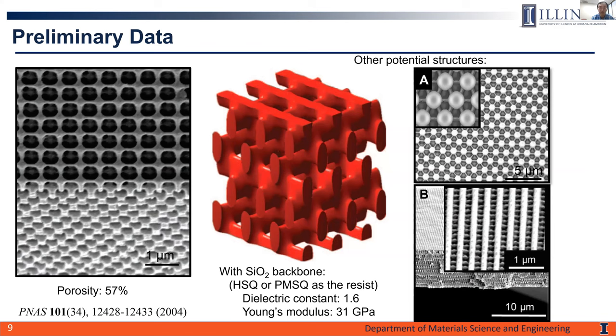So for example, in this case, we can generate a structure with porosity up to 57%. And based on the simulation, it will give an effective dielectric constant down to 1.6. So it's below the target of 2. And at the same time, we're also going to maintain a pretty high Young's modulus of 31 gigapascal. So that's only 3 times lower compared to bulk silicon dioxide. So these properties make it very attractive to meet the performance requirement we have for the low-k dielectrics for not only interconnects, but also for chip packaging.